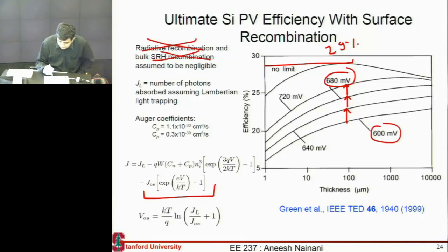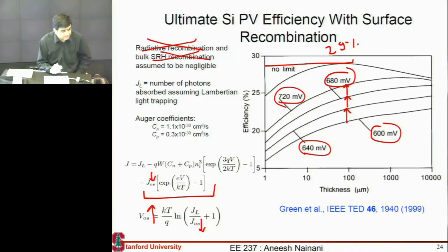So whenever you reduce your recombination, you lower this J01 term, right? So you lower this term over here, and your VOC is essentially given by this formula. If you lower your recombination current, your VOC increases, and it has this log dependence. So for every decade of improvement in your off current, you see a linear increase in your open circuit voltage.